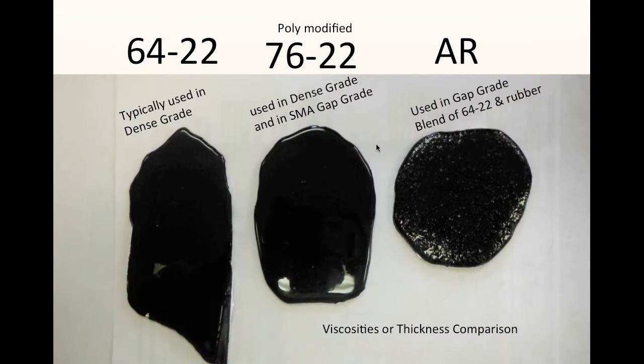And here we're just taking a look at the liquid asphalt. 64-22, these numbers are ratings that the Superpave system has come up with. It's called a performance grading system. The numbers are actually temperature ranges. Originally, the system was based on temperature ranges. 64-22 is typically age-old asphalt cement we've been using. The center is the polymer modified I was discussing.